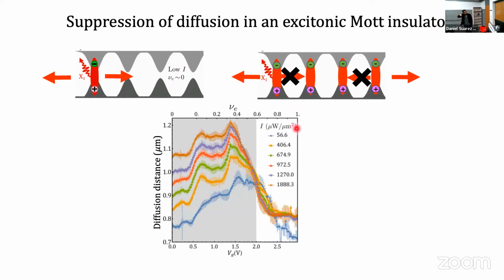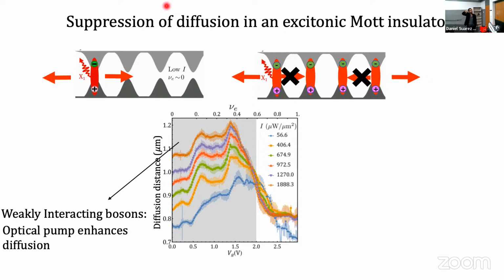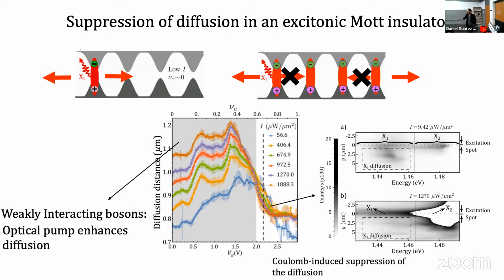So if we reconstruct the full picture by modulating the density of electrons in our system, so changing the filling factor, one can observe that as we increase the intensity of the pump, the system behaves as expected for a low population of electrons. It behaves as expected from a weakly interacting gas of bosons. One increases the pumping power, so we have more and more bosons, and then the diffusion distance increases. So this is expected from a weakly interacting gas of bosons.